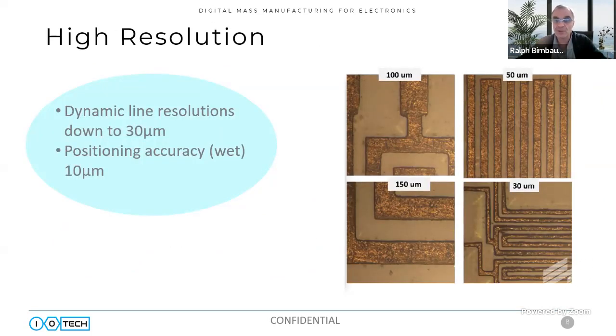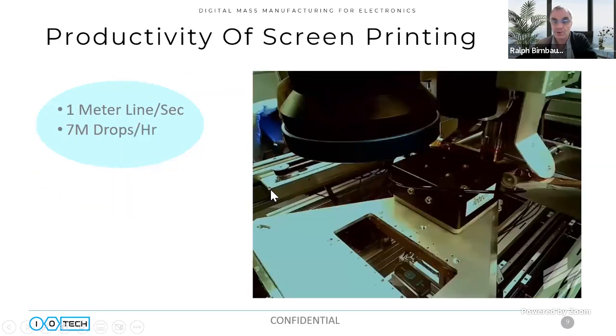Resolution, so there's dynamic resolutions. We can go down to 20 or 30 micron. We actually print a little bit higher than that, but we can ablate excess material away. And also very good accuracy. Productivity is 1 meter line per second or 7 million drops per hour. To give you an idea of how much that is, jetters will print between 70 and 100,000 drops per hour. Here we're printing almost 2 orders of magnitude greater, 7 million drops per hour.